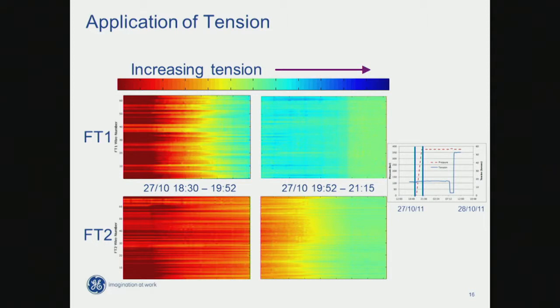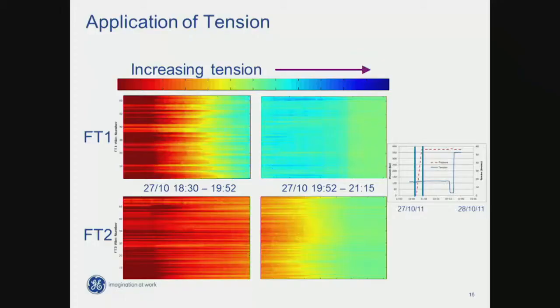Maybe there's a bit of a time constant, not just between the layers, but within the pipe. We heard a bit about that this morning. For sure, with wires, the steel, the time constant's very fast. We put a load on it, it responds very quickly. Polymers are different. And in this pipe where you've got polymer layers, you've got friction, perhaps things are a bit more complicated than your analysis would expect. So what you have here is uniform load. The two layers get to the same spot eventually, but there's a time constant and a variability across the structure before you get to there.